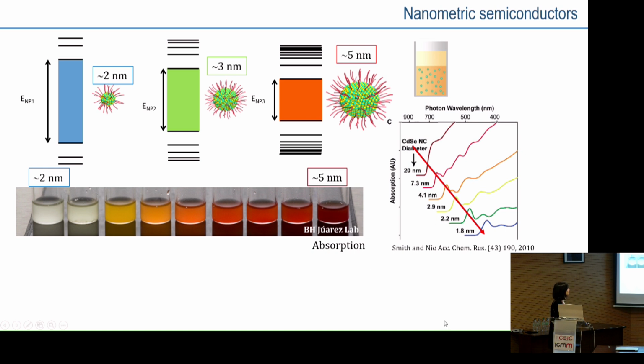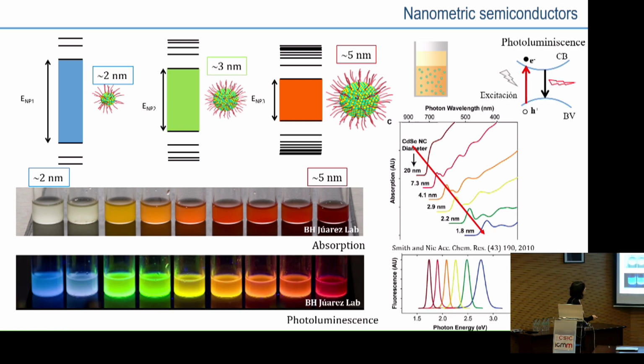Of course, if you take the absorption spectra, you observe the shift in the absorption edge. As these particles also show photoluminescence, under UV light excitation you observe this very nice photoluminescent response, giving you very narrow size distributions, very sharp and very defined colors.